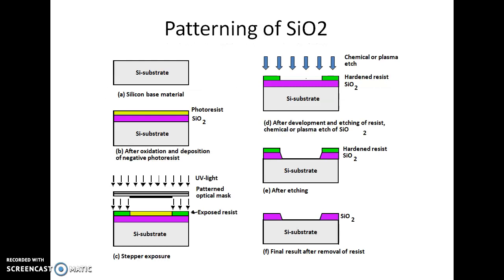These are the steps in photolithography. First, a silicon substrate is taken, oxidation is done, and silicon dioxide is deposited, on which photoresist coating is done. Photoresist is a viscous liquid polymer applied to the top surface of the oxidized wafer. It is applied by dropping or spraying a small volume of photoresist onto a rapidly rotating wafer — like an ink-filler type object — so that a thin uniform film is formed on the surface.